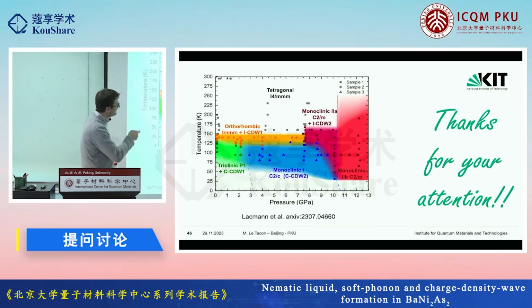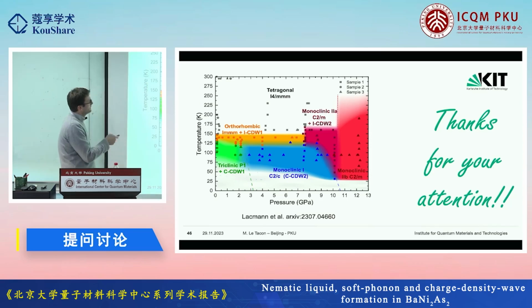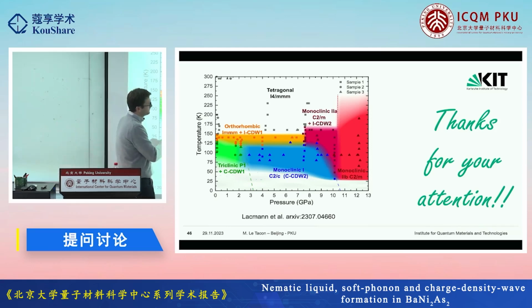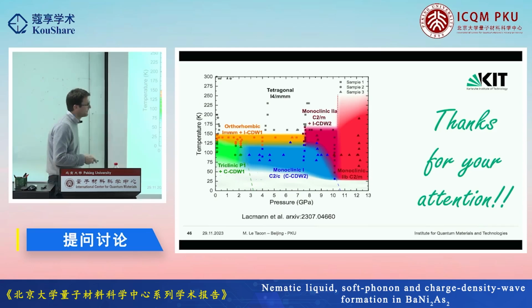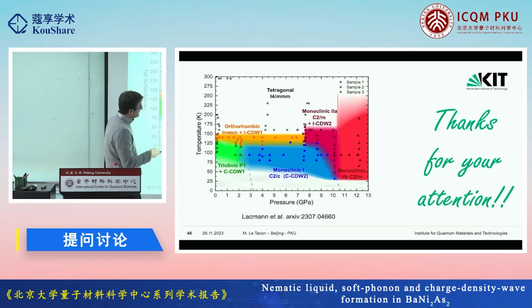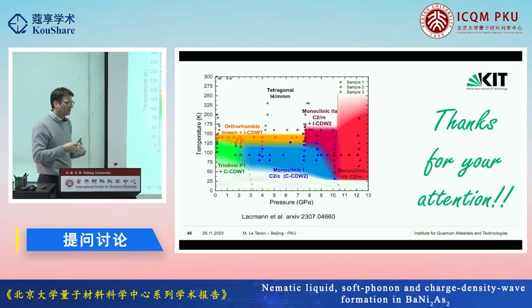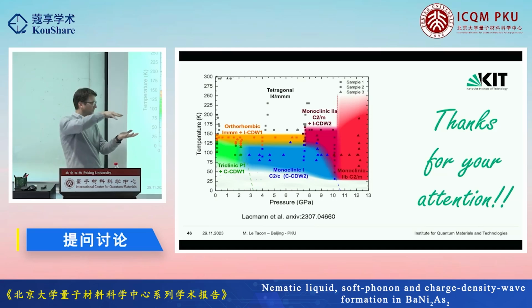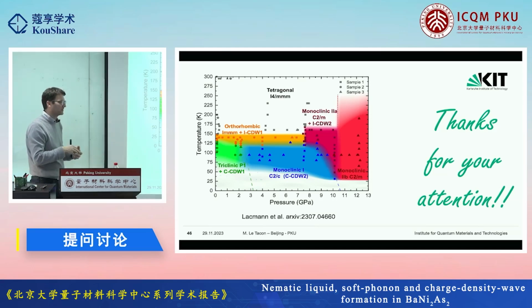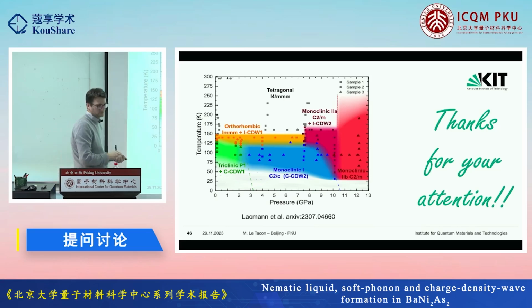We mostly looked at it from the isotherm, and then we just have a few isobars, and basically here we have only one isobar. And here you always have the problem that if you go too high in temperature, well, we didn't want to go too high in temperature, so I don't know. But this one is super weird. I can show you more after that about the shape. It has a completely different pattern, and the underlying structure is actually a monoclinic structure. So it has some kind of a collapsed monoclinic phase, we call that. Instead of having a collapsed tetragonal phase, you have a shear motion of the nickel arsenic planes against each other.